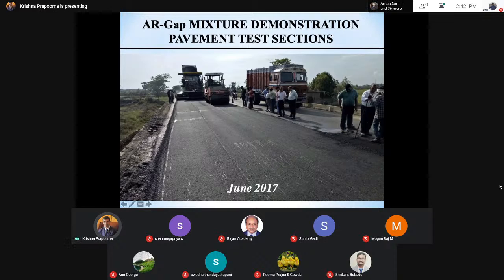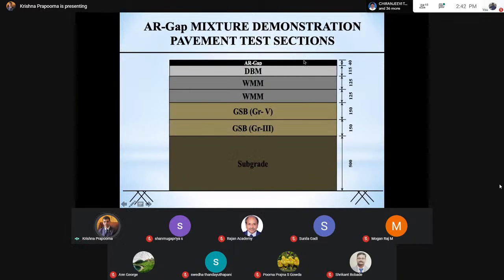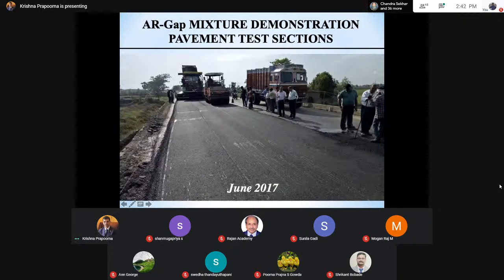And one important construction practice that you should understand, for any thin section, this is a general thumb rule. Okay. And some of you from the construction industry, if you are here, and if you're going to advise some of your colleagues and friends, when you have a thin section such as this 40 millimeter, 50 millimeter, or even 30 millimeter, okay, don't use a vibratory roller. Use only a static steel wheel. If required, only use pneumatic tire. Otherwise, just use a static steel wheel, run the required number of passes, and finish off the compaction.